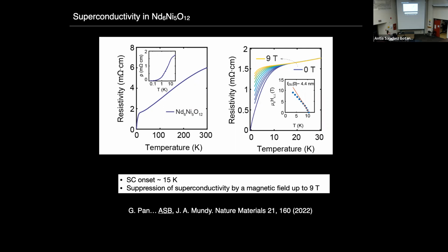What you see on the right is the same bit of the magnetic response, where we have a suppression of superconductivity upon a magnetic field that is applied perpendicular to the plane of the sample all the way up to 9 Tesla. One can get from here the coherence length and of course also the critical fields. They are very similar to those of the infinite layer compound as well.